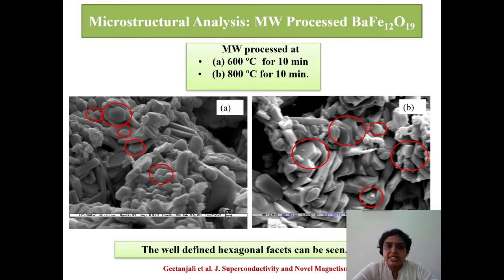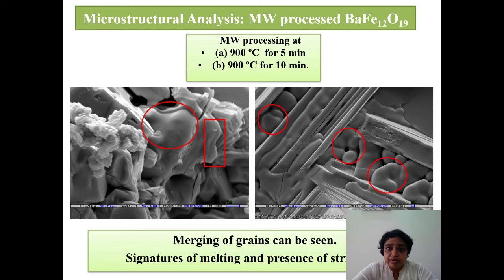Here you can see the very well defined hexagonal facets. So this is all well crystallized. So striations are also seen if you see. However, if we go for higher temperature, like 900 degrees centigrade, just merging of grains and signature of melting is also seen in samples which are processed for just 5 or 10 minutes.